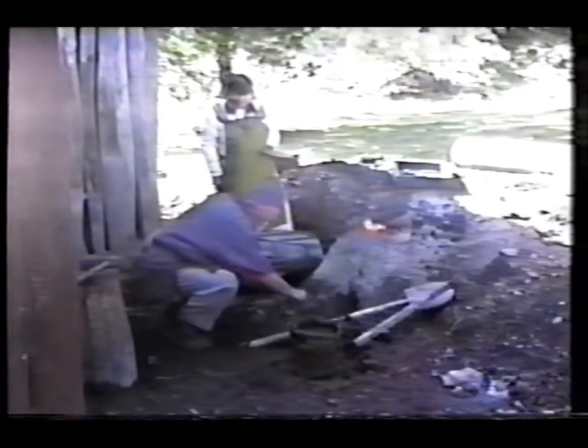And here the trusty crew are nearing the end of the smelt. After 6 hours of graft, starting at 8 a.m. in the morning, it's now just after 2 p.m. And experimental blooms show that 5 to 8 hours will produce a reasonable bloom. Would be fairly typical. 6 hours is a sort of good average.